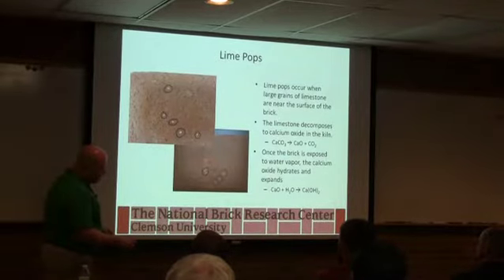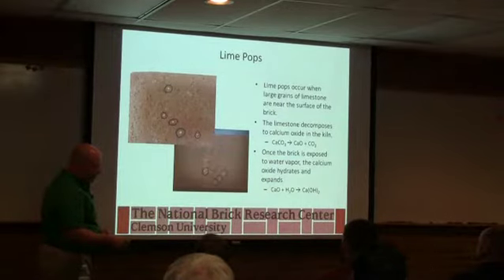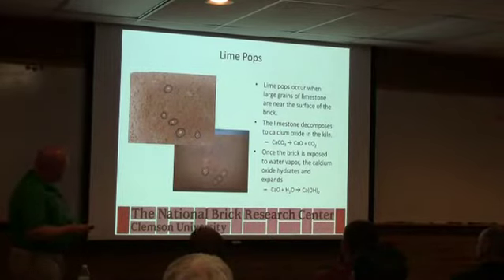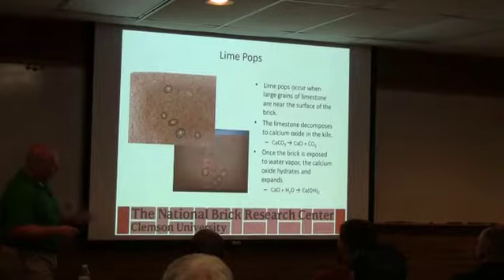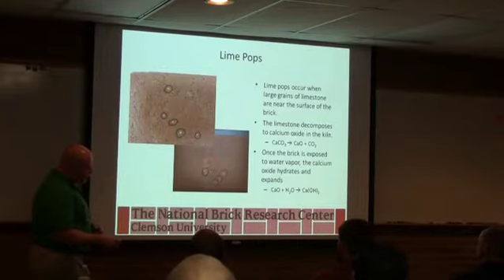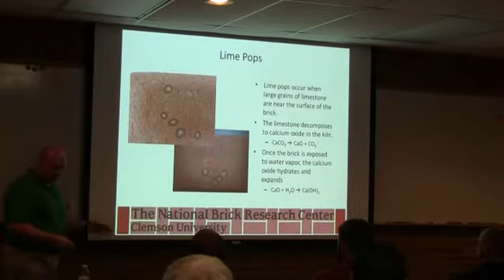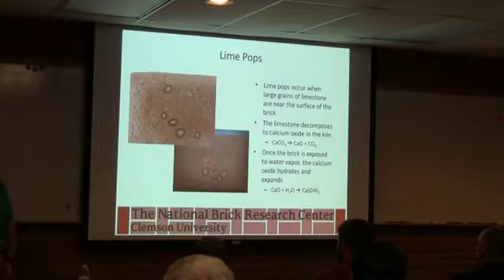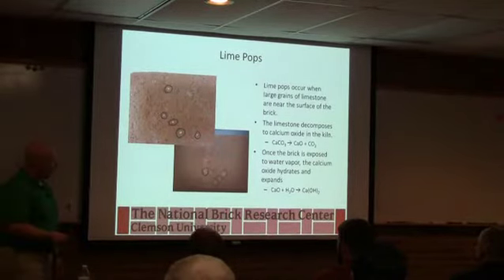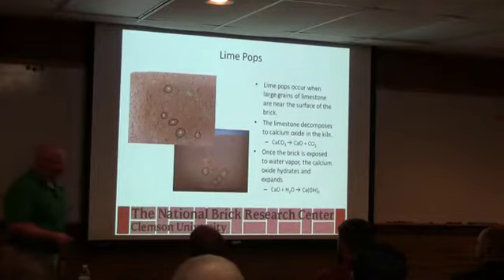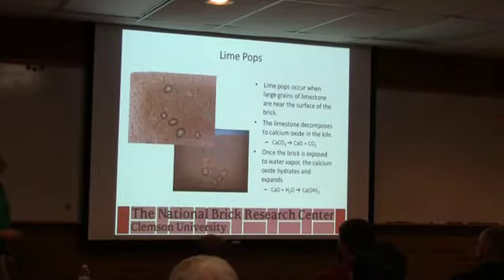When you are cleaning brickwork after you lay the brick, most of those cleaners have some hydrochloric acid, and basically it's doing the same thing it does in the raw material. It's forming calcium chloride and getting rid of carbon dioxide, but it will break down the mortar and let you wash it off the brick without damaging the brick if it's done right. We get a lot of cleaning complaints too, where it's not done right. So always want to be very careful if you're dealing with acids like that. But that's what causes lime pops.